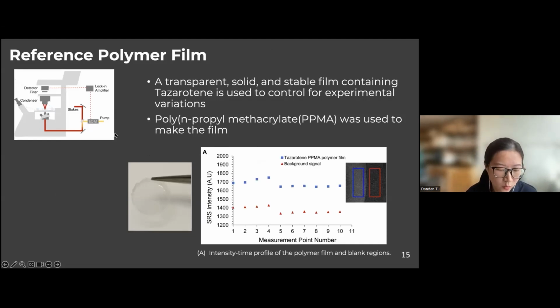In this study, to better use coherent Raman imaging for bioequivalence study, we developed a reference polymer film. The purpose of having this polymer film is we want to have a standard material that can help us remove the day-to-day signal variance, and also remove the signal fluctuation caused by maybe the optical system, some interpretation, or maybe some signal fluctuation caused by the electronics that we were using.